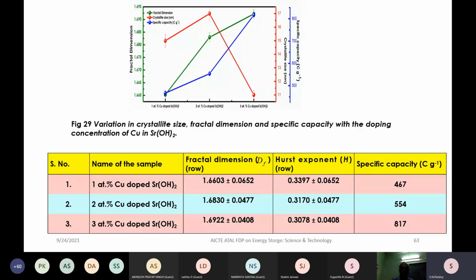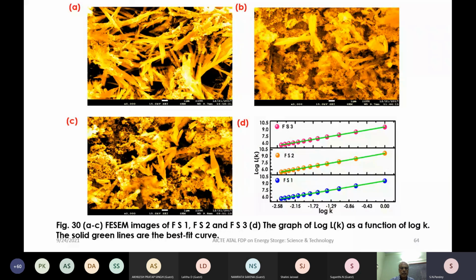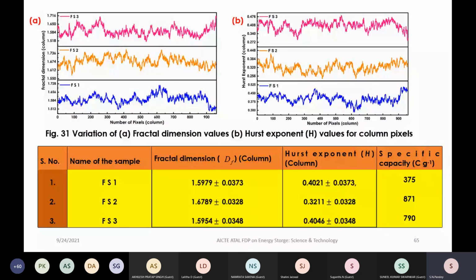So we have applied this another curve for this iron doped strontium hydroxide. Here also we are getting the straight line, which means it is showing the fractal characteristic. And then we have calculated the specific capacity, and one can see that the fractal dimension of this Fs2, the 2 atomic percent doped iron strontium hydroxide, is